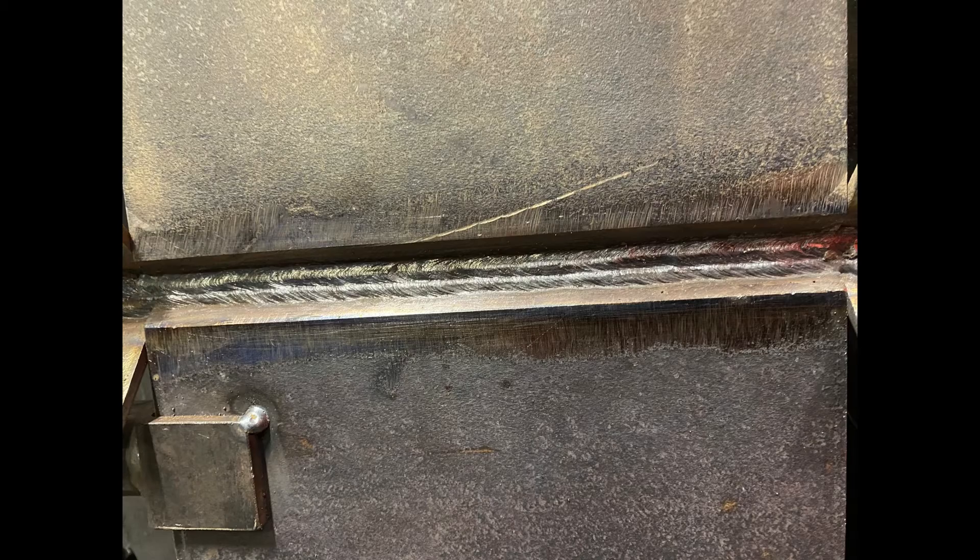Working our way down. As you can see the rod angle there, slightly pointing up. Two runs, hot pass, nice and flat, no slag inclusion, no tight areas.